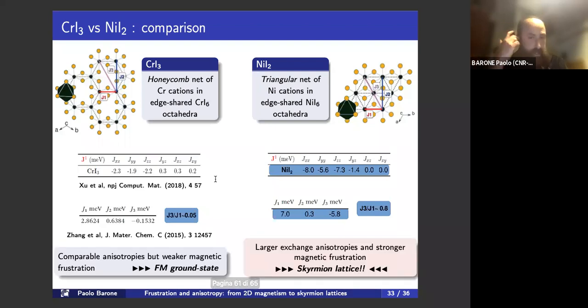Of course, the smaller frustration of the system is responsible for the fact that in chromium I3 we have at the end an effective easy-axis magnet with a ferromagnetic ground state, whereas in the nickel diiodide, the interplay of the strong magnetic frustration and this large frustrated exchange anisotropy drives the spontaneous formation of a Skyrmion lattice.